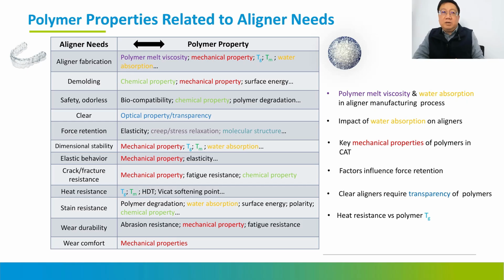This is very important. The major trend right now is that they use multi-layer, because in the multi-layer, whether outside or inside, in this kind of 3-layer they use elastic material in the middle or on the outside to provide the elastic behavior. This creates better crack resistance and also recovery.